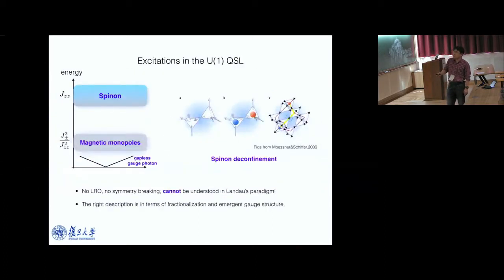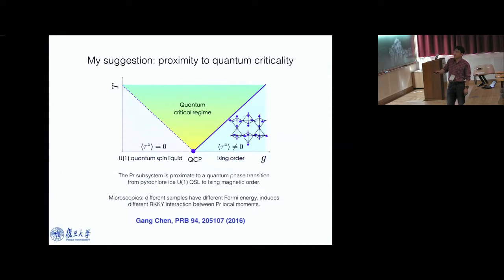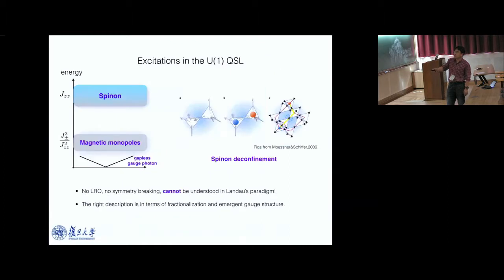So this is the confinement-deconfinement transition. Why is it a confinement transition? The reason is the system develops some kind of magnetic order by forming this 2-in-2-out magnetic order. So you can no longer separate these spinons, the defect tetrahedra, along the pathway without costing too much energy. As you try to separate these spinons, each time you move a spinon apart, you flip a spin along this pathway, and each time you flip it, it costs finite energy. This energy grows linearly with the length of this string. So the spinons are confined, and you cannot do this separation anymore.